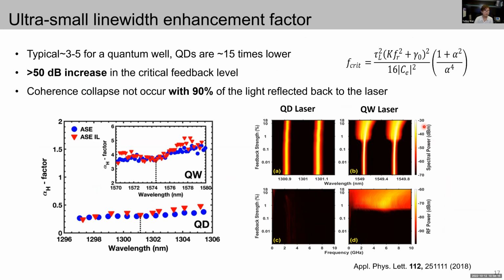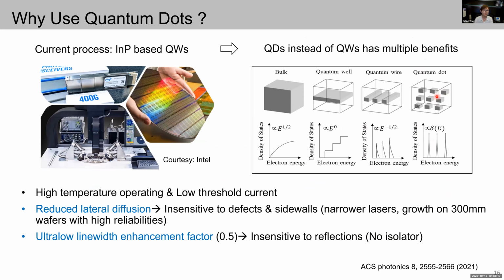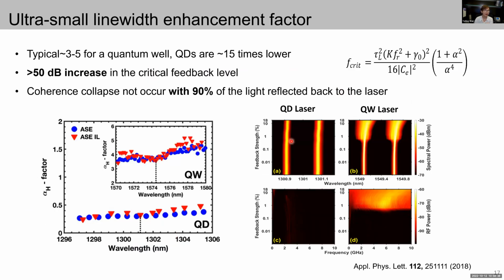Yeah. The quantum dot has three-dimensional confinement, so it has a delta-function density of states. This reduces the lateral diffusion, and it gives a very small alpha factor. As for why we have better tolerance to coherence collapse: coherence collapse is determined by a critical feedback level, which is related to the alpha factor. The smaller the alpha factor, the larger the critical value. We can measure that the quantum dot has a 10 to 15 times smaller alpha factor, and this 15 times smaller alpha factor corresponds to a 50 dB increase in the critical level. The larger the critical level, the better the tolerance to feedback, so it doesn't have coherence collapse.